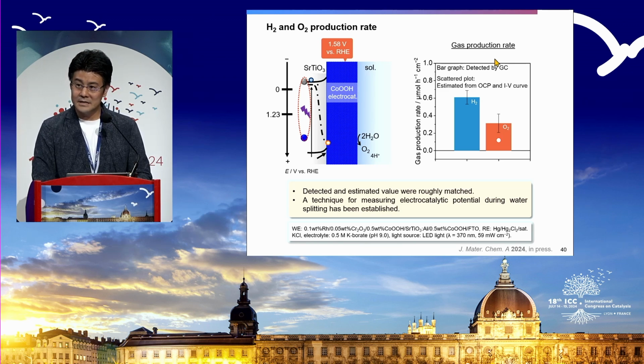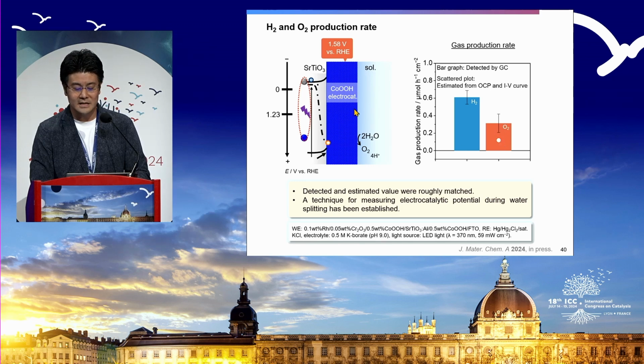And if you measure the gas evolution, this one is actually coming from the oxygen evolution from the electrode. So this point is not matching, let's say only 40% is coming from this cobalt oxide. That is okay because here you're already generating hydrogen and oxygen. So 60% is still coming from overall water splitting. Part of this hole is coming to this electrode, and that's how we say it matches. So we think that this way, we may be able to estimate the potential, what is happening on the surface of photocatalyst powders.